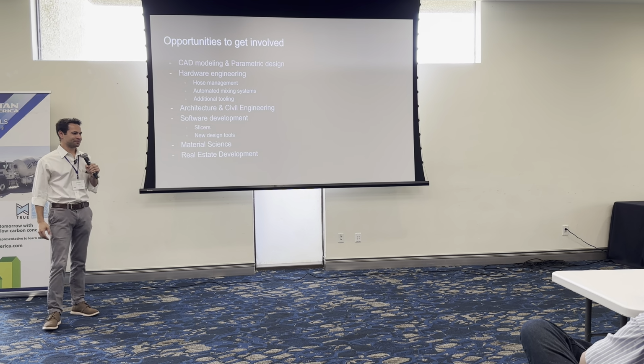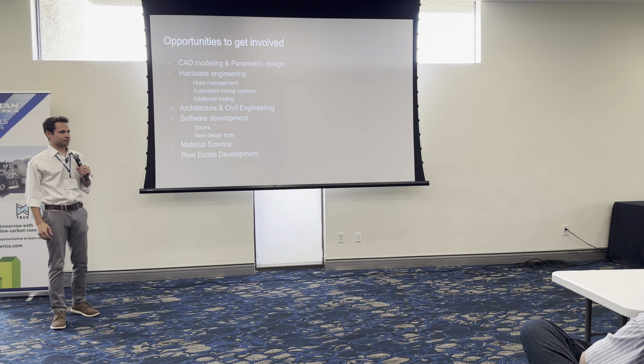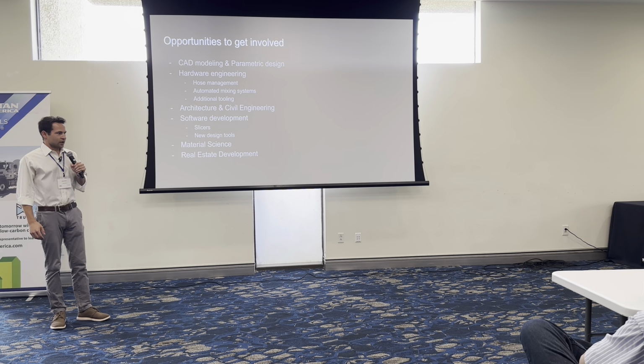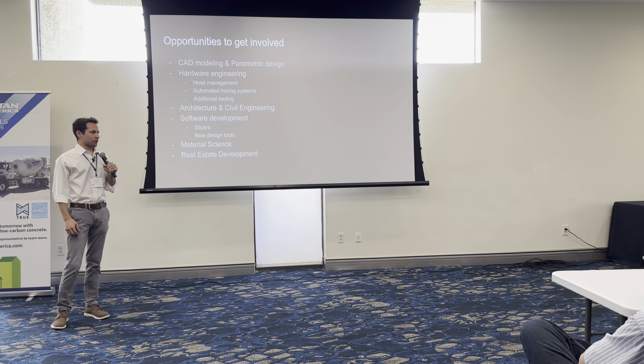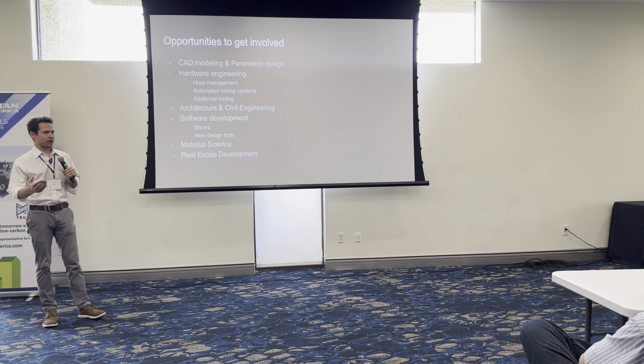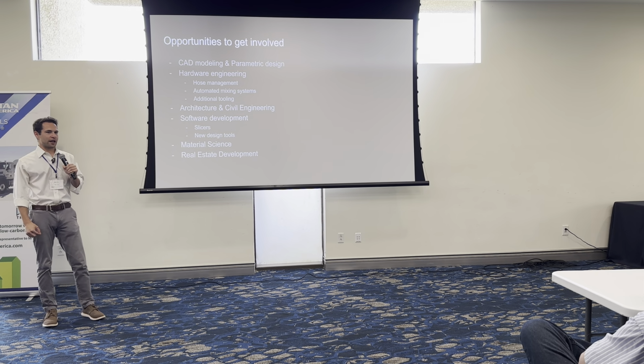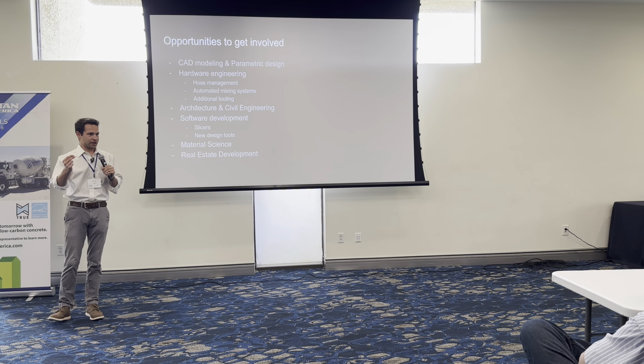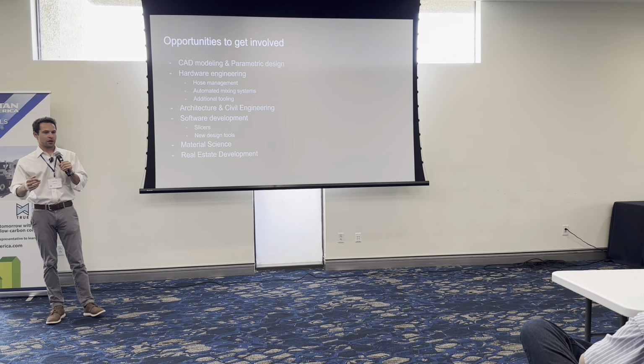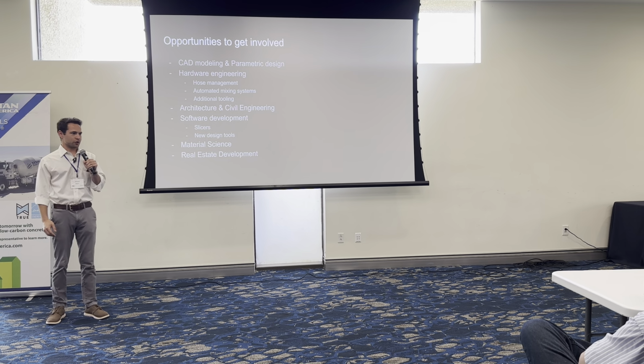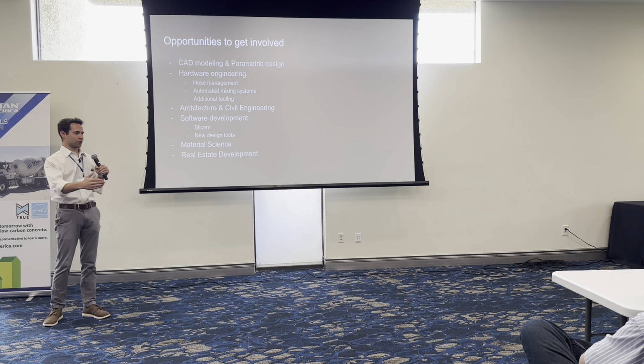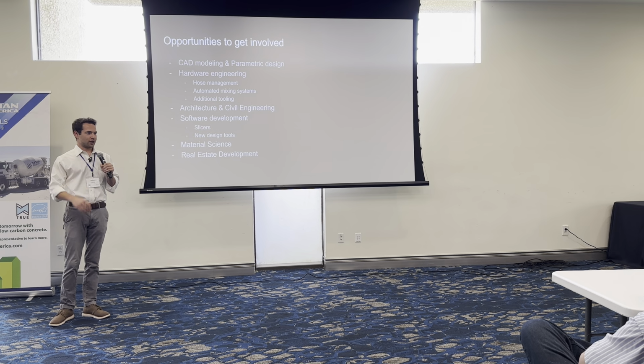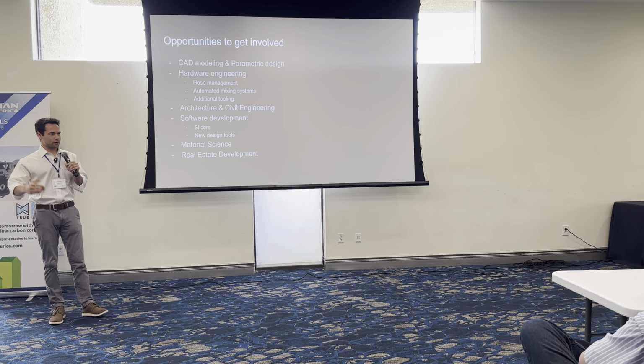Last question. Has fiber reinforced concrete been used in this? Yeah, they do use some fiber reinforced concrete. They've tried the metal fibers. They've tried polypropylene fiber. It's challenging because it makes it more sticky in the hose. And so the more fibers you use, the higher likelihood of a clogging event in the hose, which is horrible. If it clogs, they'll have to bring out sledgehammers or flush out the hose, or maybe the hose is just garbage. So they generally don't use fibers in the mix.